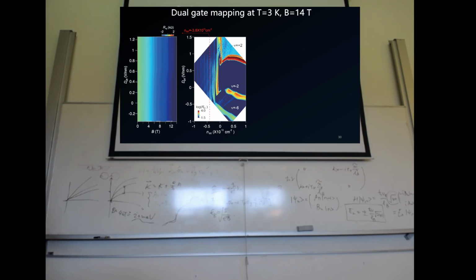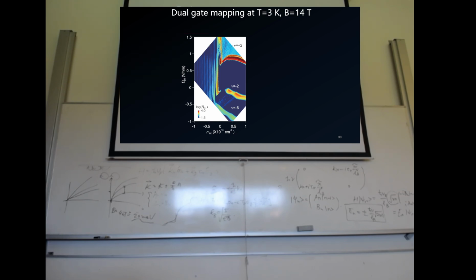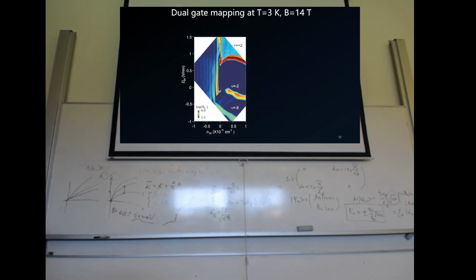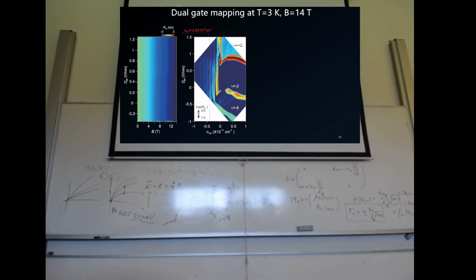But let's first put the sample under a magnetic field and see how the Landau levels look, and then we'll have a clearer idea of the phase boundaries, for example. So this is how it looks. It's the same map as this one, but instead of no magnetic field, this one is under a magnetic field of 14 Tesla at 3 Kelvin temperature. So you can see that there are several phases clearly distinct from one another.